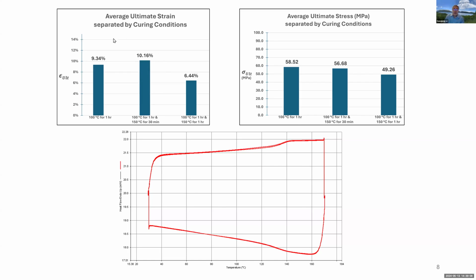Okay, you can see the difference in terms of the fracture strength and also the difference in terms of the ultimate tensile stress. Based on this, you can see that this curing condition seems to give us a little bit higher tensile failure strain, and also the tensile stress is not that low. The DSC test result shows that the glass transition temperature is about 130 degrees Celsius, which should be proper for infrastructure use.